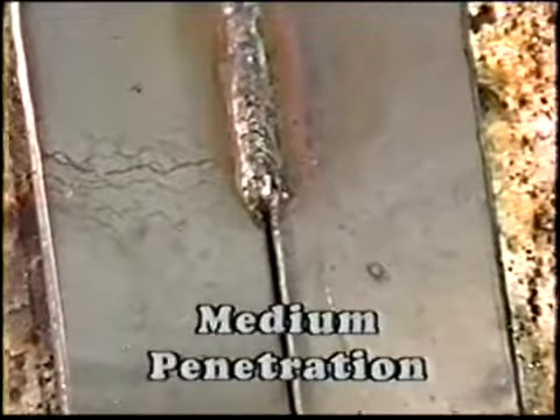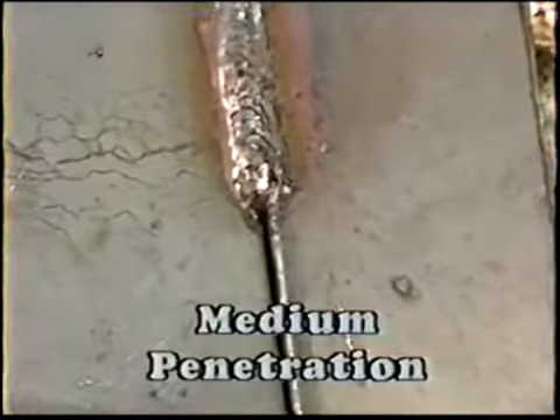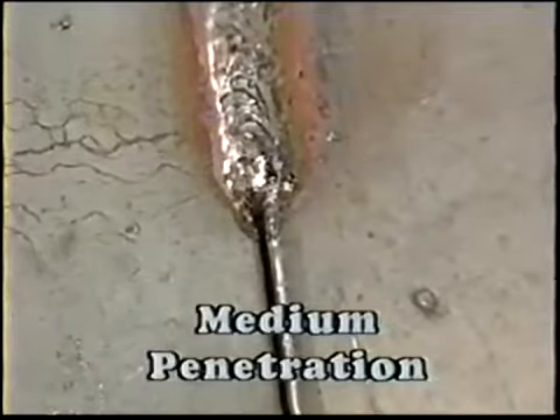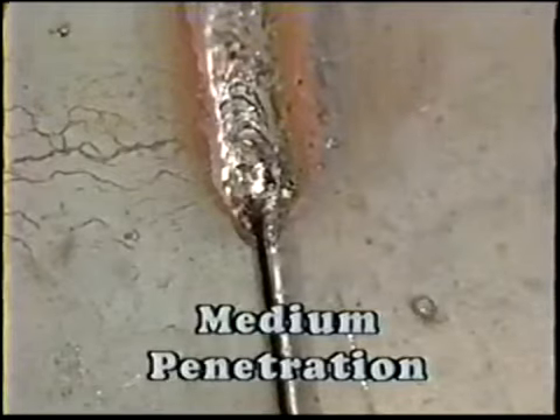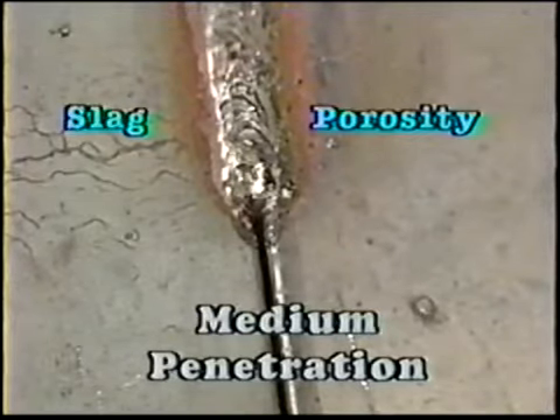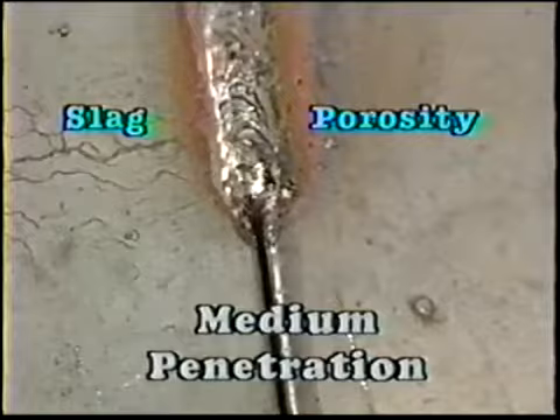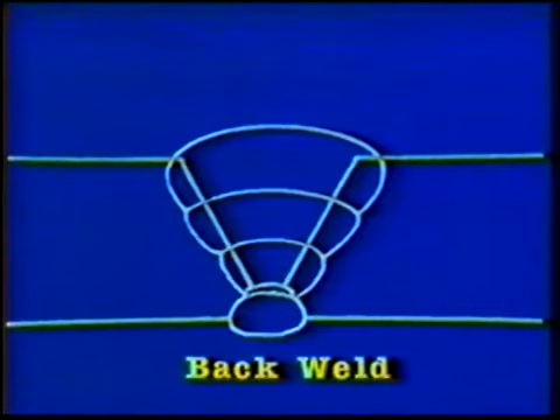These electrodes have medium penetration characteristics, and this requires extra precaution when welding a root pass with a root opening, since there is a tendency to trap slag or to produce porosity. Whenever possible, use a tight root opening to deposit the weld. After welding, the root pass is back gouged down to the point of sound weld metal, thus removing any slag or porosity that may exist. Then a back weld is deposited on the root side of the joint in order to produce complete joint penetration.